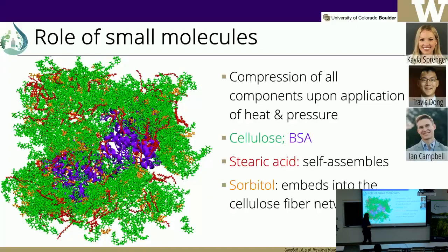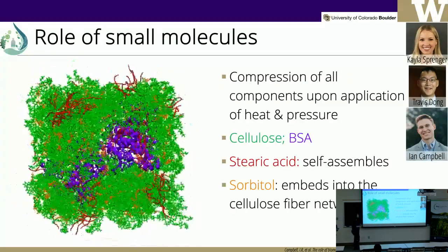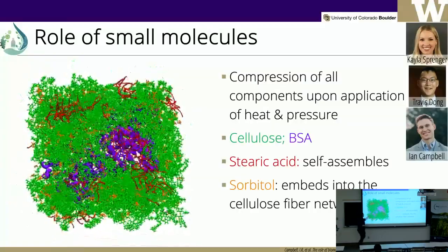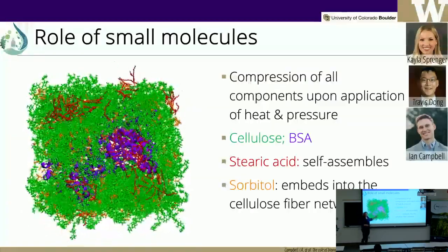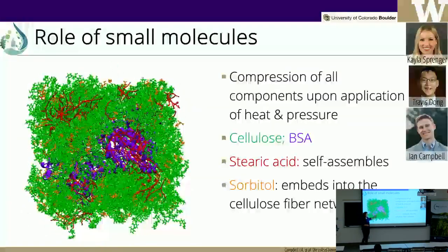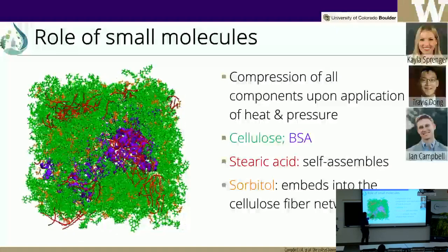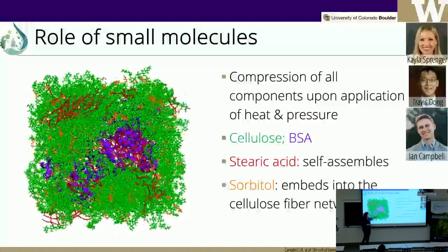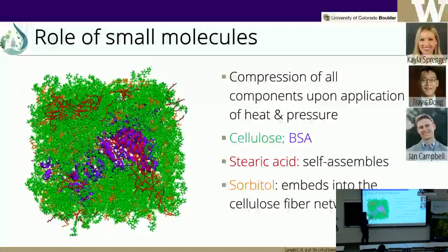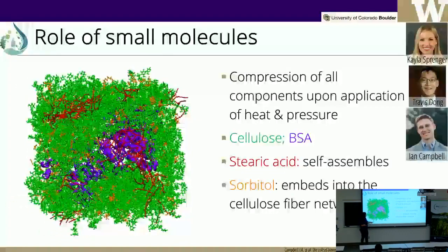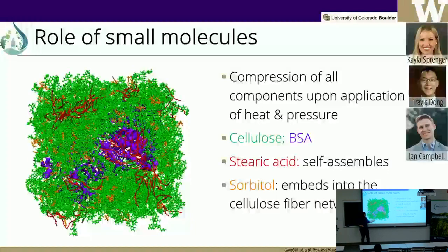Then as we subject the system to heat and pressure, we will start seeing that indeed we should expect some crystals to form. This is actually confirming the SEM images that we had. So stearic acid will not interact with anything else but itself. It will self-assemble. Then our sorbitol is going to go everywhere, plasticizing the matrix. Actually, not everywhere, primarily within the cellulose domain, even though there are some that interact with the protein.